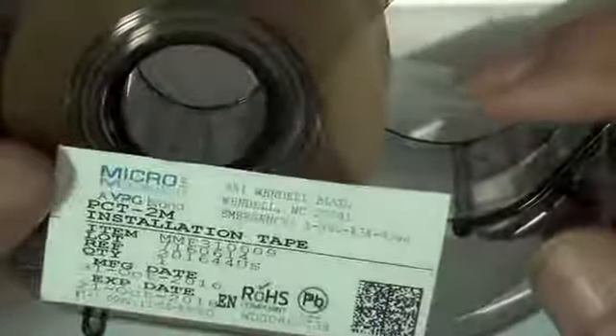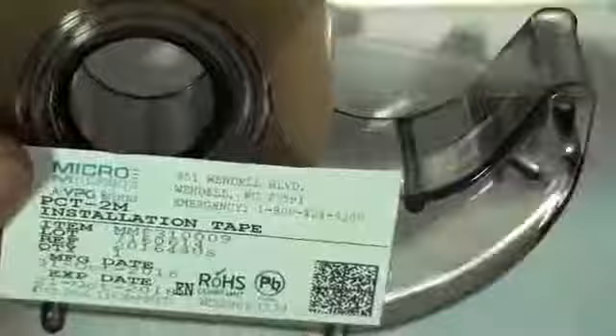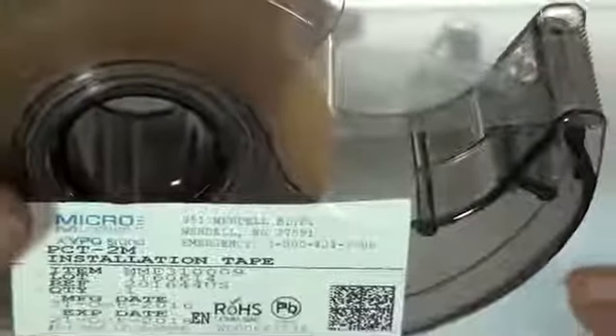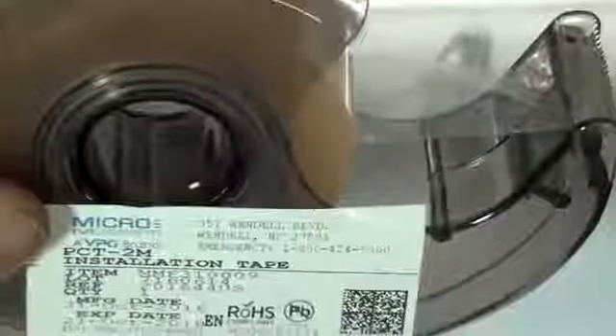It's a special tape picked out from a large number of tapes available in the commercial market. It has the property of not leaving its mastic on the surface, so the surface doesn't get contaminated when we use this tape. And that's the main reason why we use this tape and not any other cello tape. Right. With an ordinary tape, it's possible to put the mastic on the surface, and then the gauge will stick on top of the mastic. It will not bond, and we have failure.